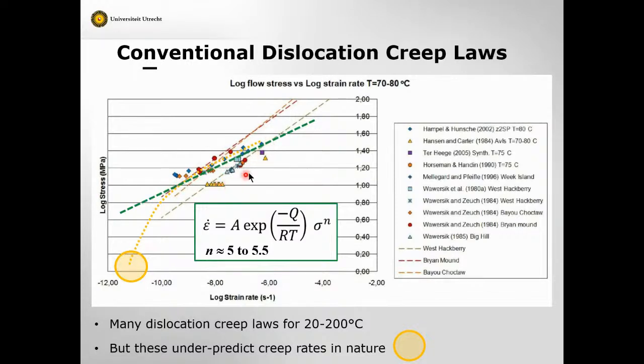Here are typical data from many different studies at this kind of temperature range, of typical temperatures at a few kilometers in the crust. And that's all. This can be described very accurately with all sorts of empirical laws, and very typically a Norton type power law with an n value of around 5 will fit salt creep data very, very well when dislocation creep is going on.